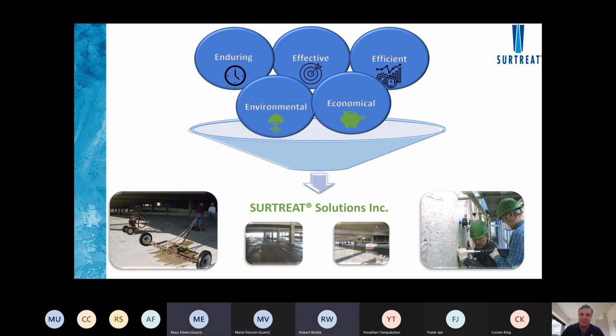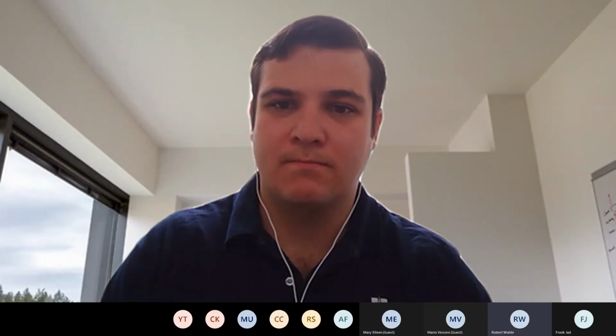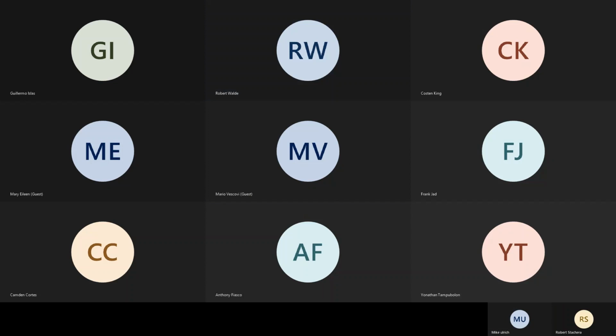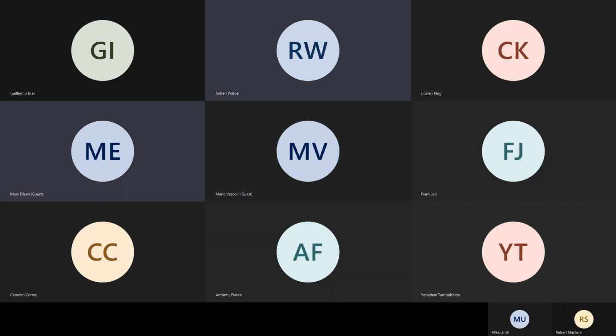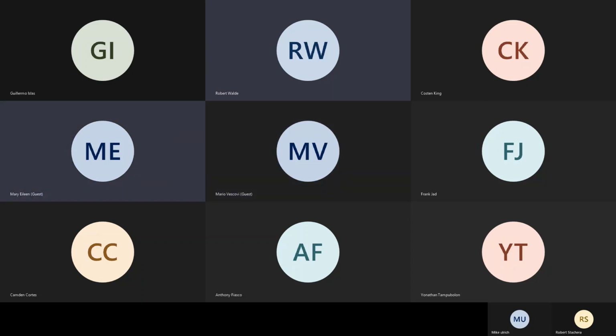I just have two things that I might want to add to expand on what you had presented. When the new concrete comes in with a pH of 13, that creates a corrosion passive film on the rebar. When it drops to 11, it goes into a corrosion active state. And the damage is caused by the fact that the rust that's being formed occupies 6 times the volume of steel. So it's the expanding rust that puts pressure on the concrete, causing delamination first, then spalling.